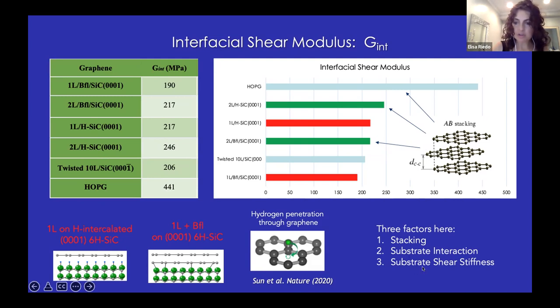Finally, the substrate shear stiffness is important. So for example, if you look at the two green here, they should have the same values. But because this one is on top of a stiffer substrate, which is essentially this structure here, compared to this one, which is on top of this substrate, then you really have an increase. And indeed, the ratio between this green and this red is exactly the same ratio as this green and this red, indicating really that the substrate simply shifts the value of the shear modulus of the top layer.